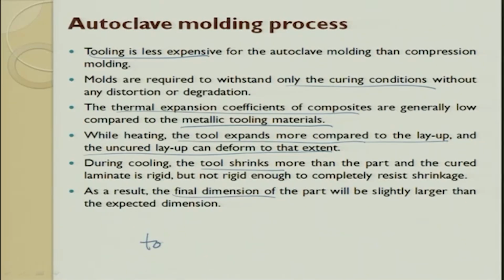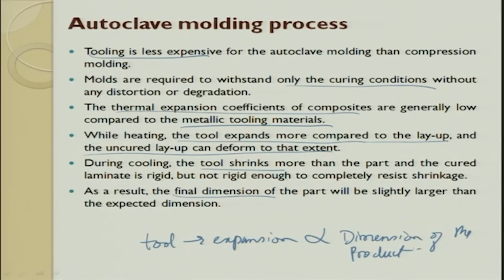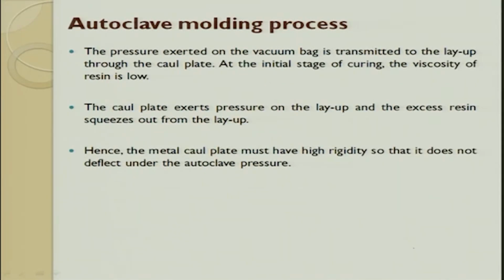So, the tool expansion has a direct influence on the dimension of the product. This has to be properly chosen. The pressure exerted by the vacuum bag is transmitted to the hand layup so that the resin can flow. The caul plate exerts pressure on the layup and the excess resin is squeezed out through the layup. Hence we always use a metal caul plate, which must have very high rigidity in the autoclave process.